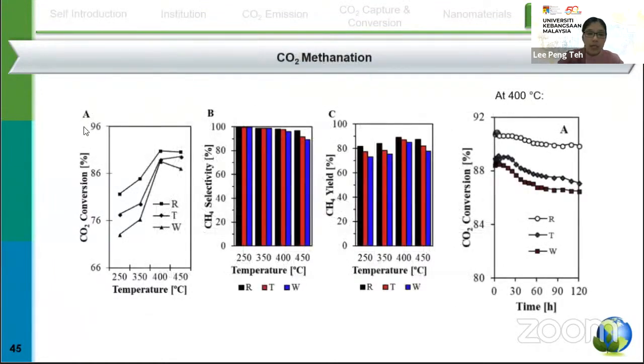And this is when we compare the three techniques. It shows that the reflux, the R, gives a very high CO2 conversion and also CH4 yield as compared to other techniques. This is due to the very high surface area, the smaller metal particle size, and also strong metal-support interactions from using the reflux technique.